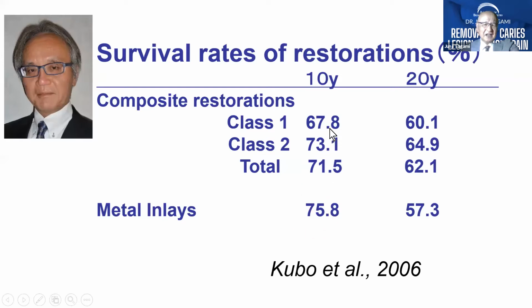And this is a part of his research on survival rate of the restorations. After 10 years and 20 years, composite resin showed 71% and 62% respectively. And this is almost the same as with the metal inlay restorations. Of course, in the textbook of the dental material, the precious metal is the most excellent restorative material. However, as a restoration, the survival rate is almost the same as the composite resin restorations.